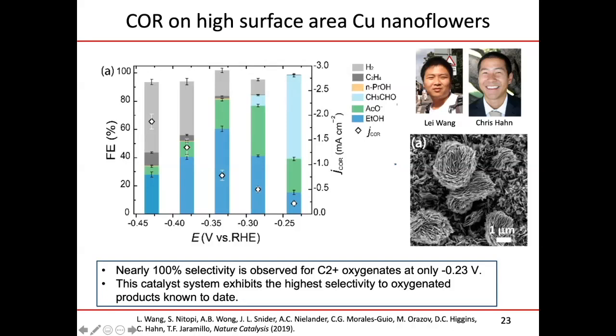Now we can operate, this is now CO reduction as opposed to CO2 reduction. We can operate very close to equilibrium, less than a quarter of a volt overpotential, or less than a quarter of a volt, I should say, more strictly speaking, versus the reversible hydrogen electrode. And almost 100% of the current density is going to C2 oxygenated products. So we're making almost no hydrogen, no hydrocarbons, and these three oxygenated molecules are ethanol, acetate, and acetaldehyde. So this is a way of just saying, just steering this morphology of the material can completely change the selectivity.